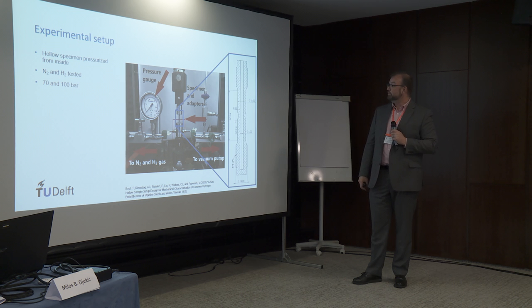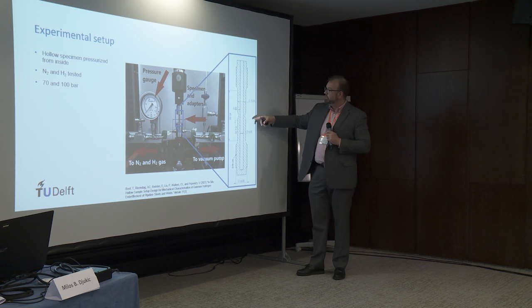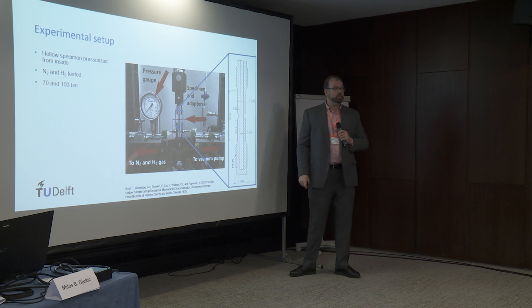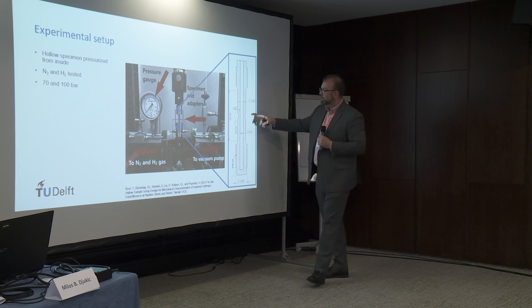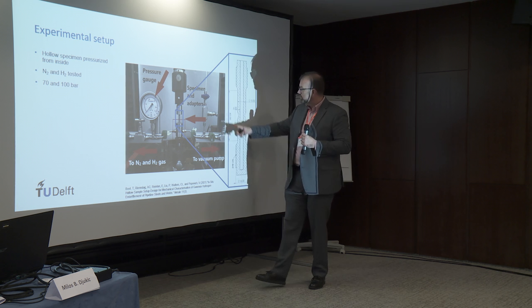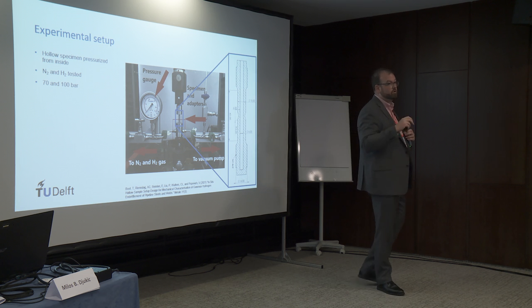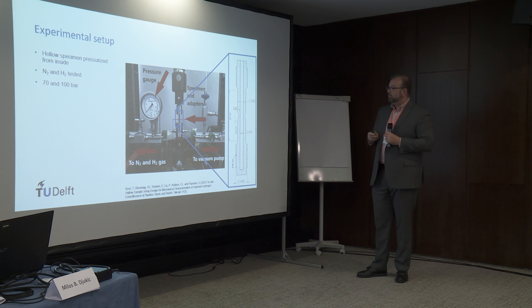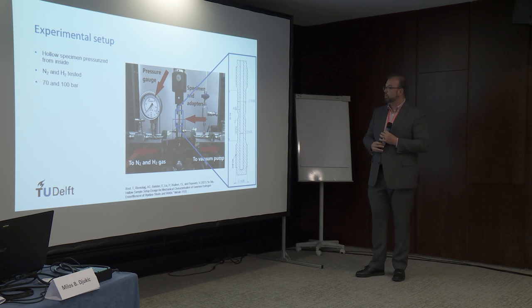This data is for a pipeline steel. What Tim did is take an axisymmetric specimen that was hollow — just a 4-millimeter diameter hole drilled throughout the specimen — and exposed it to tension. A very nice thing about the experimental setup is that we have valves everywhere, so we can load it with hydrogen or nitrogen and then close those valves. We have a very small amount of compressed hydrogen in the setup, so when the specimen eventually breaks, the volume of released hydrogen is small enough not to form a hazard.